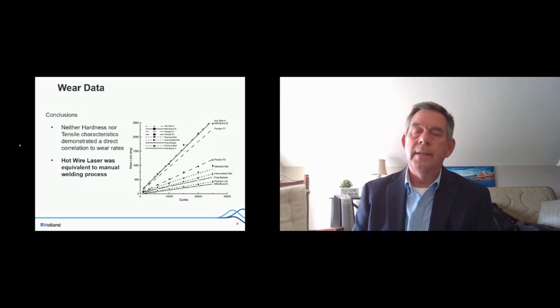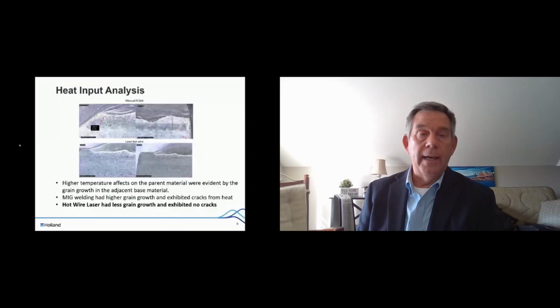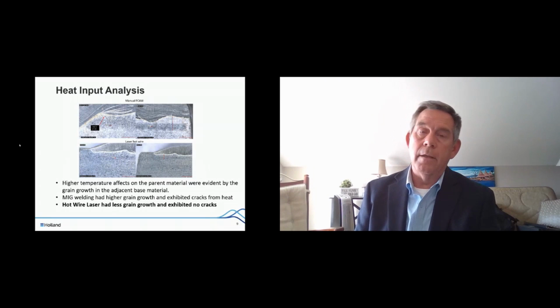The next, and one of the most important characteristics, is to look at the heat input while welding. This is a test where we again utilized MIG welding and then did a cross-section of the materials. With MIG welding, if you exceed 500 degrees, which is the benchmark that the railroads use for trying to repair a frog without exceeding that, it's very difficult to do because of the arcing process. As can be seen in the top graphs and the cross-sectional views, there was significant grain growth of the base material underneath the weld. And in fact, there was also cracking in that area because the temperature did exceed 500 degrees. So this validates the target to stay under 500 in order to produce a longer lasting repair.